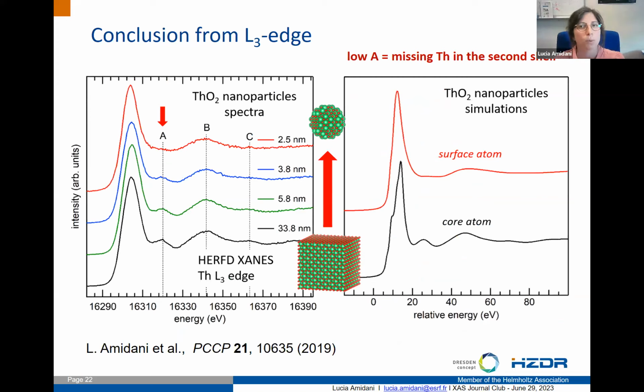But we could conclude that it was clear that the low A peak in the post-edge was clearly a sign of missing thorium atoms in the second shell. Here, it's an extreme case where we go from a core to the surface atom. And this was our first conclusion.